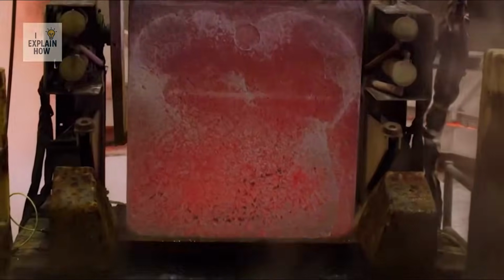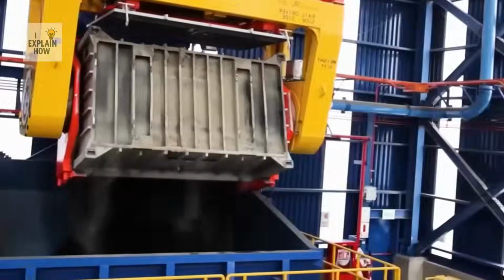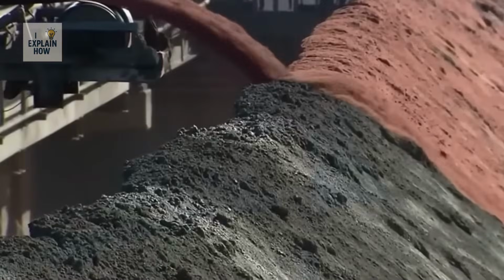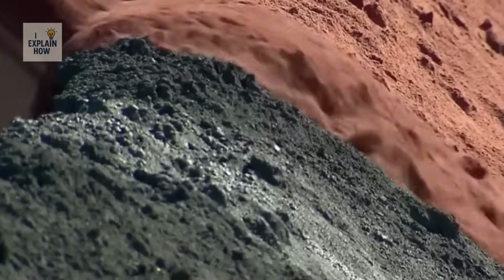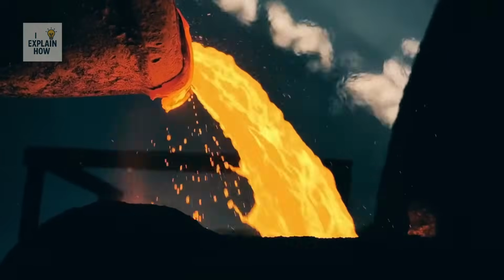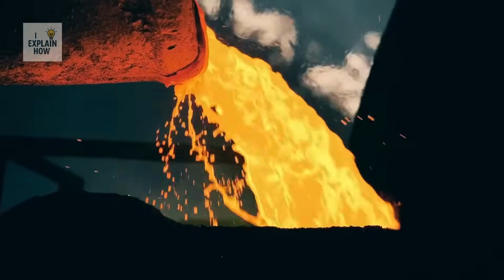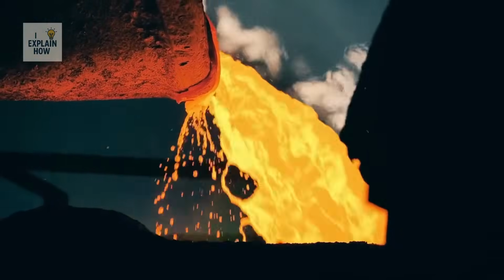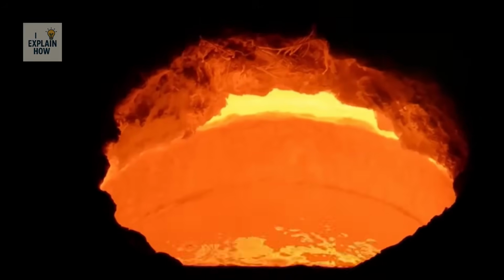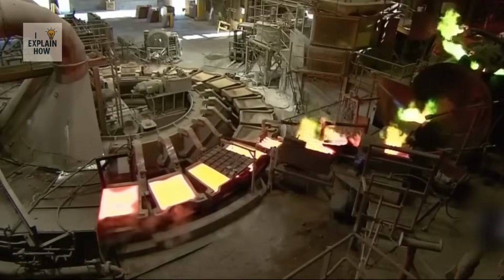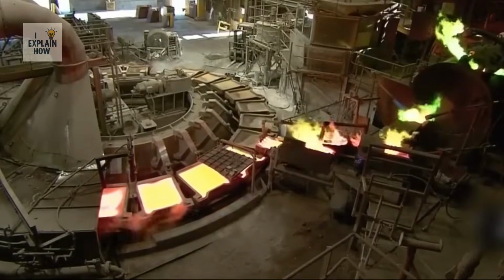The concentrate is transported by train to huge deposits where it is mixed in layers with silica sand called flux, which helps remove impurities during smelting. Subjected to extreme temperatures, the charge transforms into a molten liquid. The slag, made up of iron and other minerals, floats to the surface while the copper accumulates at the bottom.